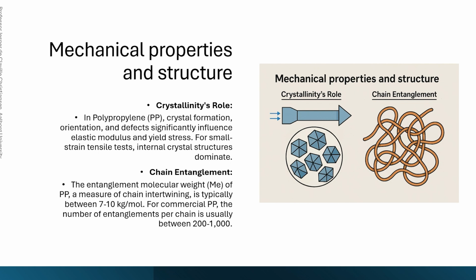In most mechanical tests that you typically see performed, they are short-term tests, for instance, tensile bars. And here the properties will be determined by this entanglement and by the crystalline structure. There's not sufficient time for these amorphous areas to disentangle. So you get properties that are mainly determined by the shape and size of the crystallites.